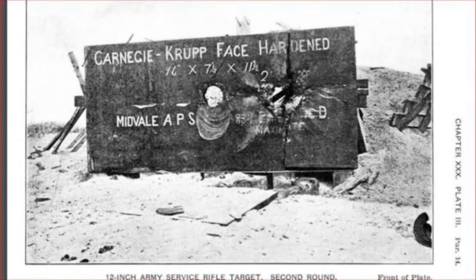Now, this result is probably somewhat less surprising to you listeners, having just heard me go on at length about the various problems inherent with having too much brittle material in your armour. However, whilst this rather absurd 80-20 ductile-brittle ratio was walked back a bit, constantly improving armour-piercing shells and a constant desire to shatter them meant that US Class A armour, which was the US Navy's designation for face-hardened battleship and cruiser armour plate, would end up having a much deeper hardened face than anyone else in the 1930s and 1940s, at a 50 to 55% hardened depth.